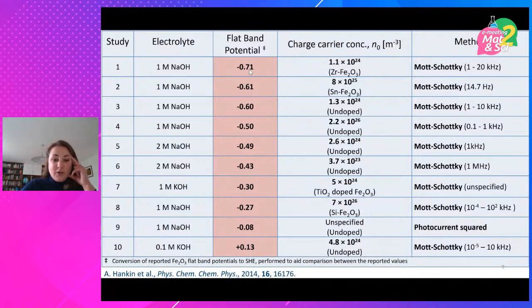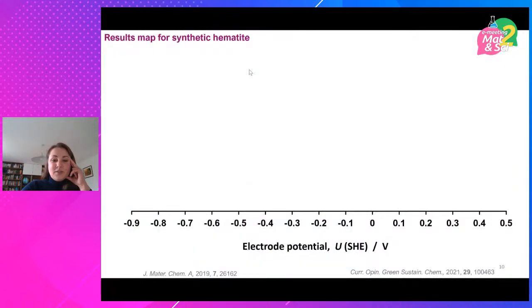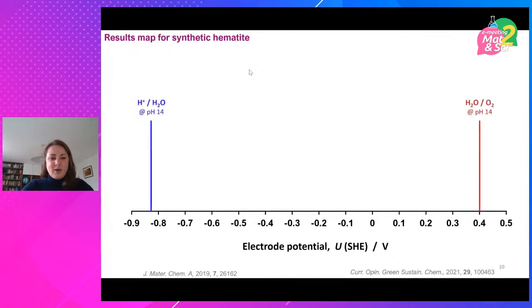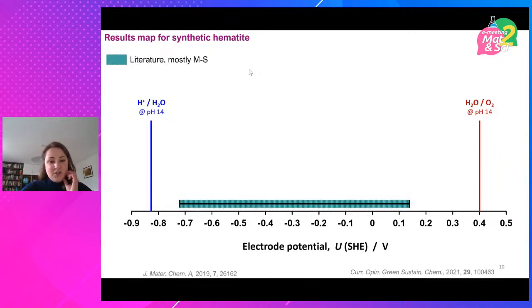So to do a spoiler alert, what happened at the end of our study when we looked at everything with Mott-Schottky and the other 4 techniques, this is what we found. So let's just plot electrode potentials on the x-axis, right? Just arbitrarily ranging from minus 0.9 versus the standard hydrogen electrode to plus 0.5. Let's mark where the solvent boundaries are. Just an example at pH 14, because that corresponds to about 1 molar hydroxide solution, which is what most researchers use for hematite because that's where it performs best and that's where it's chemically stable. So these are separated by a favorite value of 1.23 volts. So if we take all the literature values that I just showed in the table, that is the range that they span. So you're not quite bridging the 1.23 volts of solvent stability, but it's a very significant dispersion.